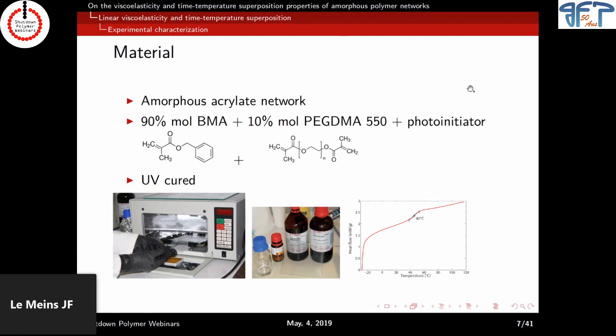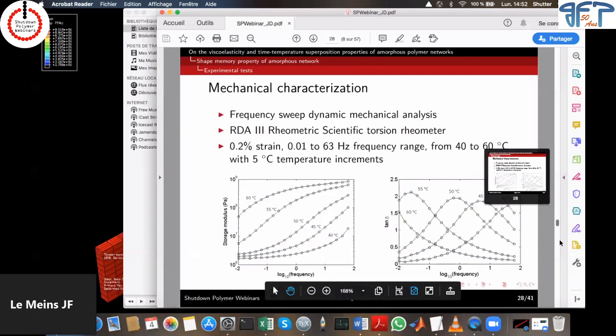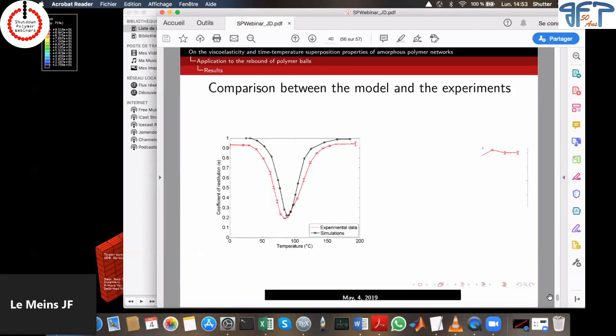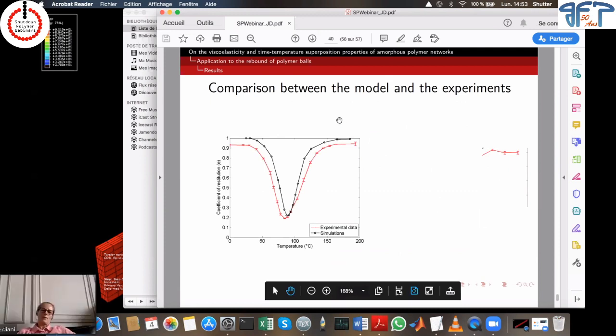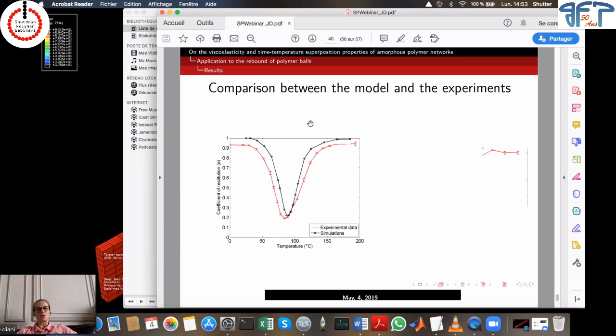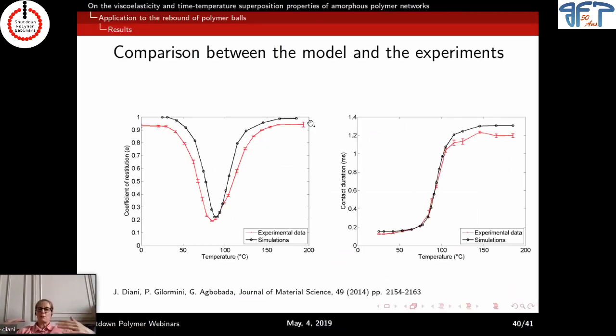Maybe I have misunderstood something regarding the efficiency of the rebound of the ball. Efficiency versus temperature goes through a minimum around the Tg. How do you control the temperature of the experiment? Oh, for the rebound, as you've seen, it's super fast, right? So what we do is that we just warm our balls in a thermal chamber until the temperature of the balls is equilibrated, and then we run the test once for each ball. We have several balls, once for each ball. So during the 10 or 20 seconds, the temperature holds. Okay, thank you.